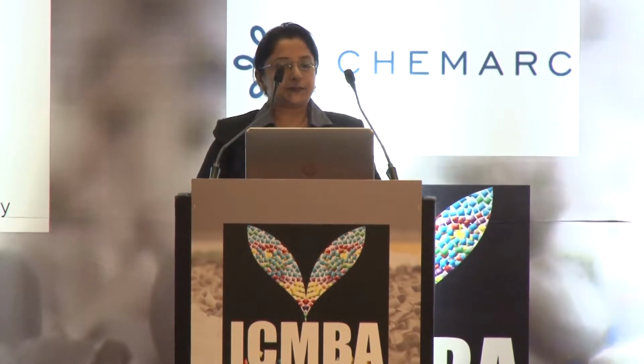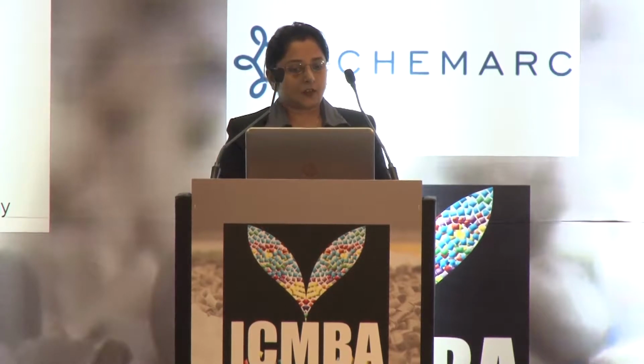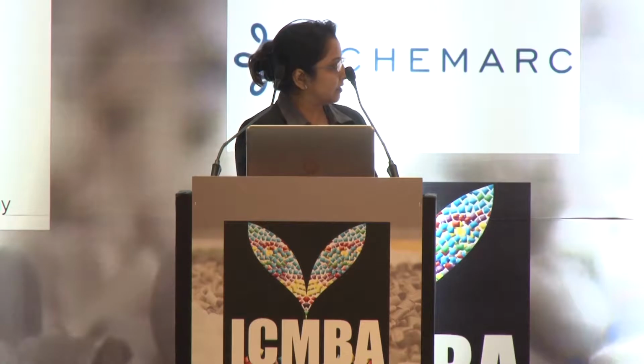Now let's have a look at few results which we have done. This is the opacity. Just to give some background, it is 60% masterbatch, which let down at 5%, 50 microns film thickness, and contrast ratio is measured as per the standard method. And if you see the second column, that's the standard. It's 3% TiO2. And if you just replace 10% TiO2 without anything, you see this effect. There is a drop in opacity, and if that 10% is managed with FP-550, then you see it is matching